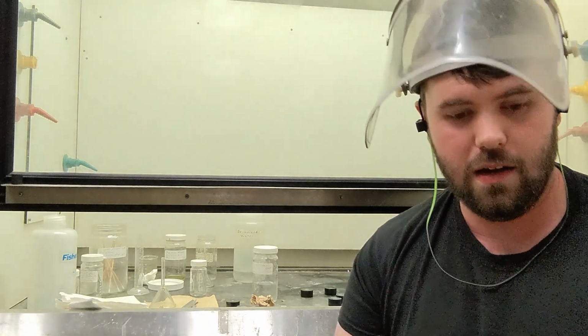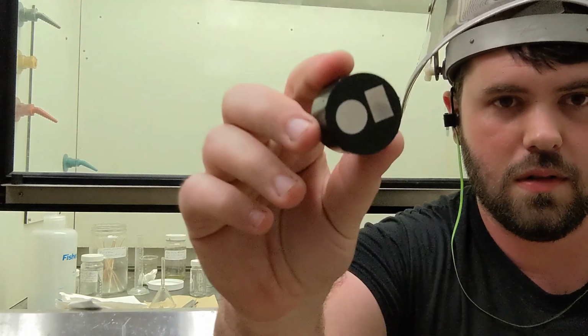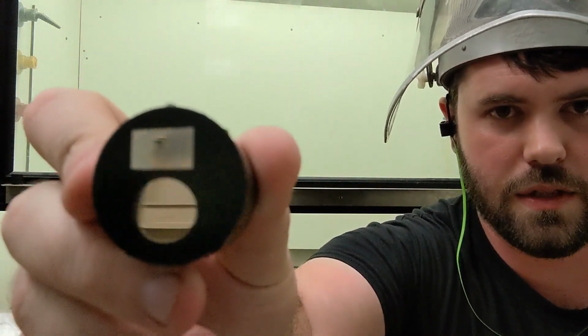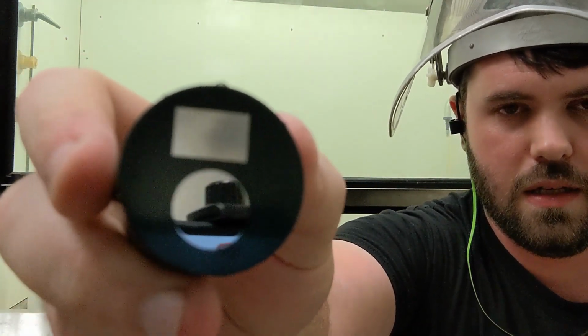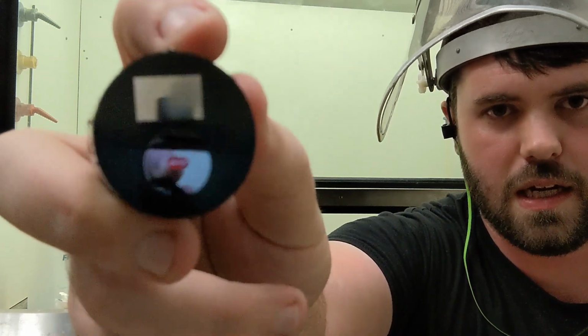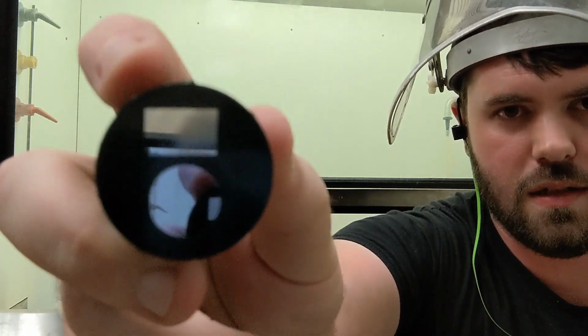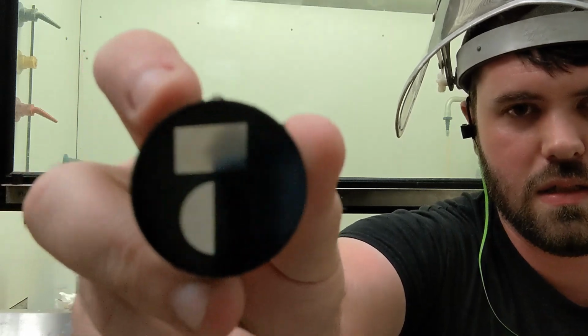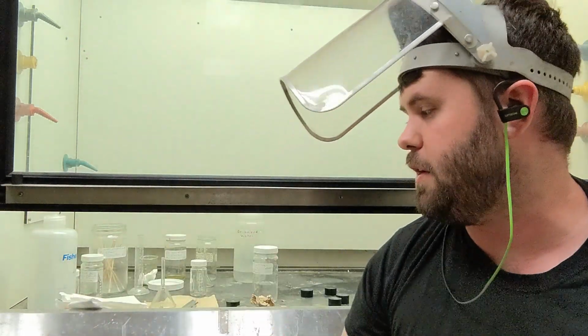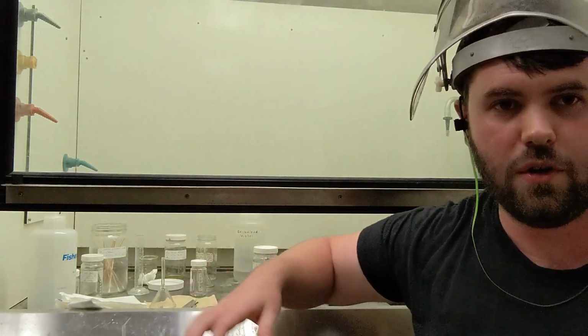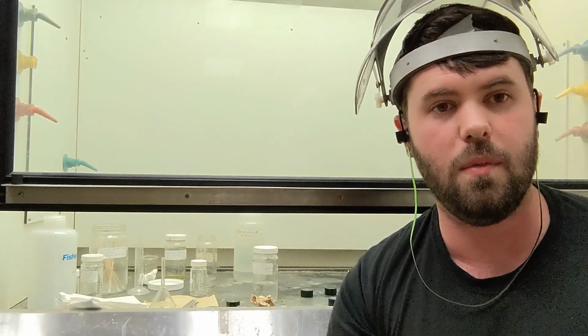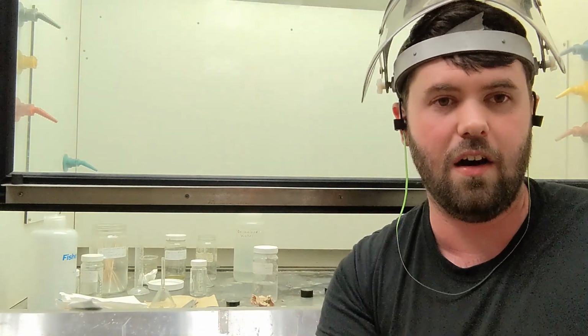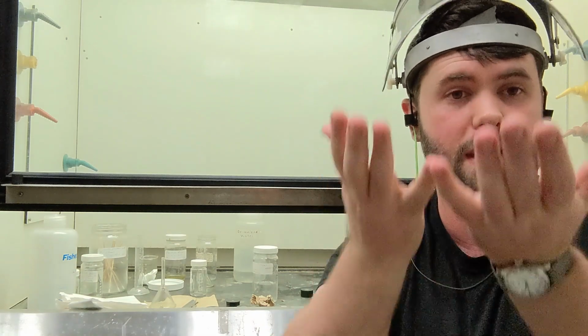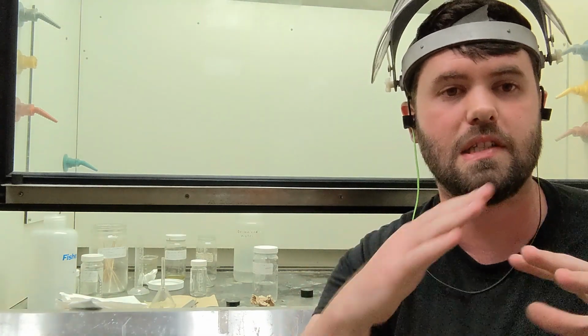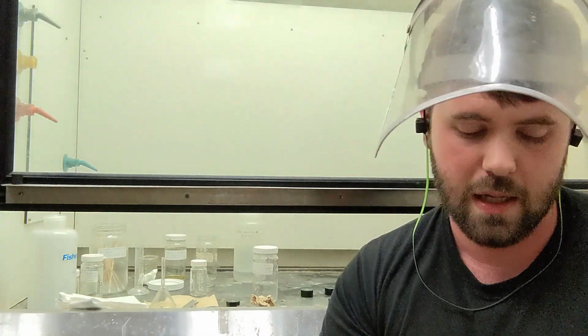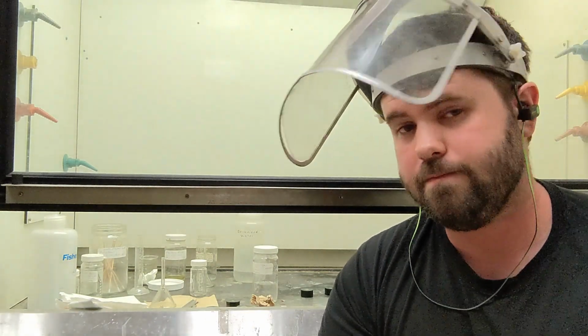And when all is said and done, your etched sample will look like this, which you can see, hopefully. So this side here is etched, the right side is unetched. And the reason why it looks cloudy is because as we reveal the grain boundaries, the surface is no longer uniform, so it is no longer reflecting light all back at the same orientation, at the same direction. It's scattering light in different directions, so it's not as shiny.